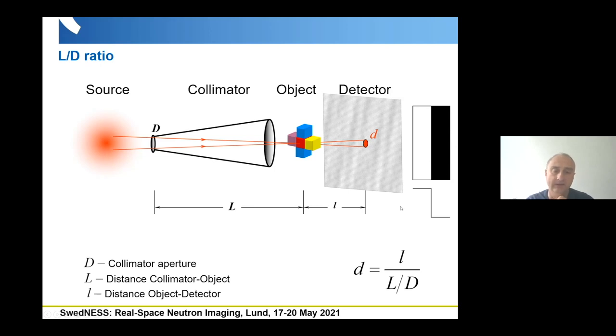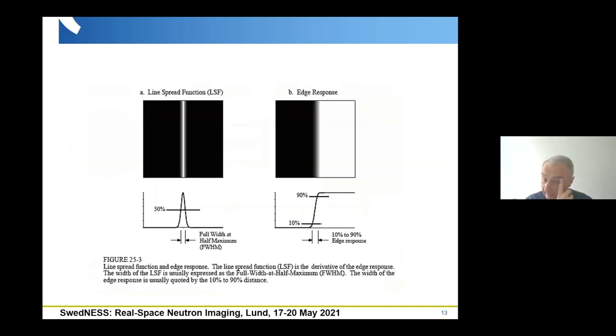In reality, it's not the case. So at least we have some pixelization of the detector. And also if the beam is not really well collimated, this means that this step function will be smeared. And this D, as shown here, is representing first the geometrical blurring from the beam collimation, and also the resolution property of the detector, where the pixelization is also giving its contribution. So you can see here two different cases.